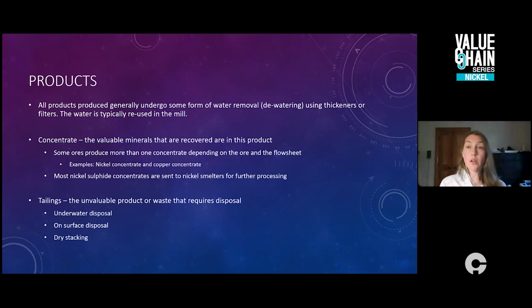However, you can do on-surface disposal, which is really creating a tailings dam to store them in. And then recently there's been a push towards looking at dry stacking as well, which is taking the tails and removing the water and being able to stack them directly on land. The water itself that is generated from this generally goes back to the mill for reuse. Water is a valuable commodity and is a precious asset to many mills, and so it gets recirculated back and starts again. So we try where we can to bring that back again to the mill.